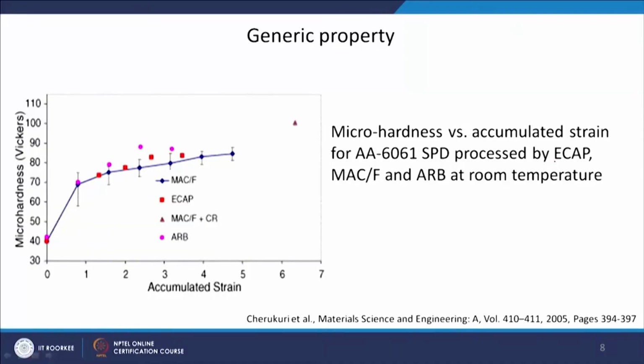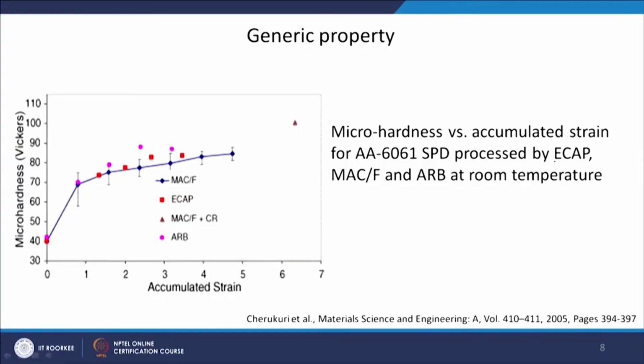Now, as we are continuously discussing this part, there is a very nice study about the effect of different SPD processes. You have ECAP, multi-axial forging, and accumulated roll bonding, and the accumulated strain in each of these processes was noted down, and its effect on the micro hardness is plotted here. You can see there are 4 different conditions. One is multi-axial forging, ECAP. In this case, after multi-axial forging, cold rolling was also done. CR is cold rolling here, and the fourth process is accumulated roll bonding.